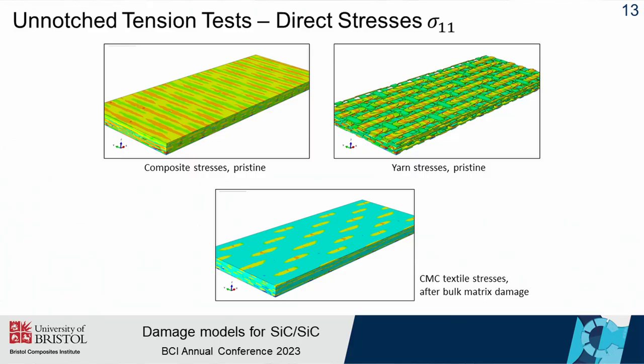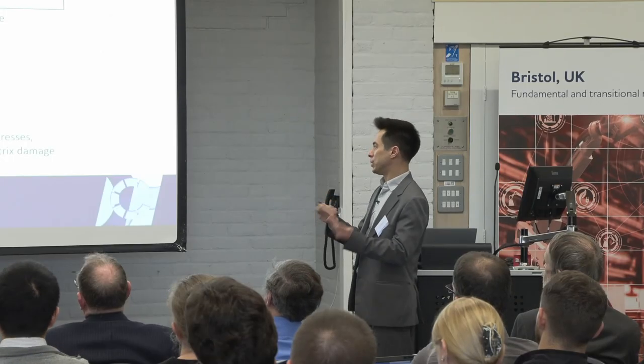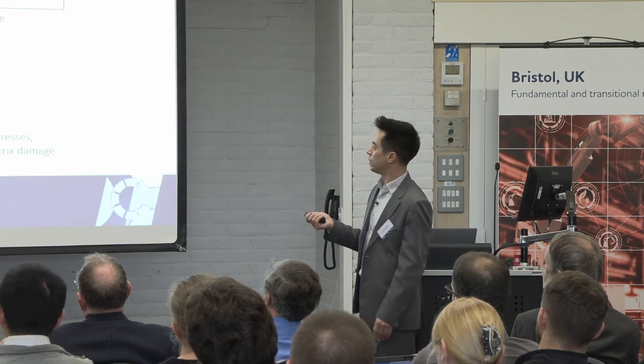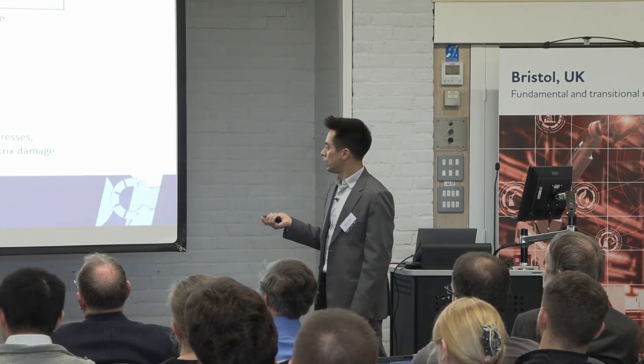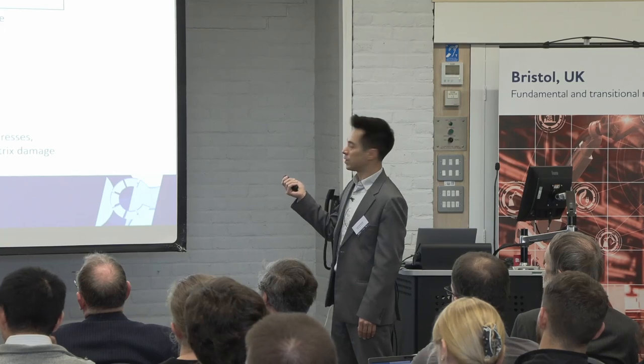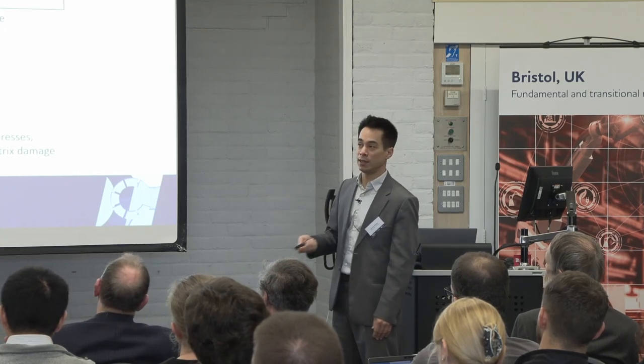Some contours of stresses, the nodal values, just to show the effect in the elastic regime of that voxelization of yarns and fiber volume fractions and material stiffnesses. You can see the stresses being different between weft and warp yarns and also the matrix, okay? So both in the pristine case and after some damage develops.